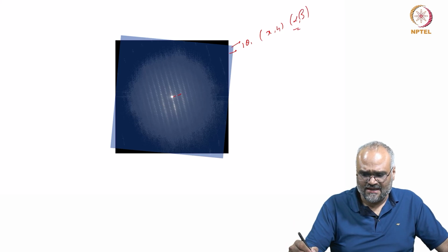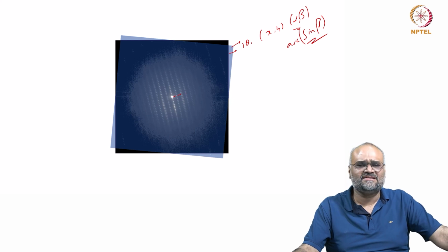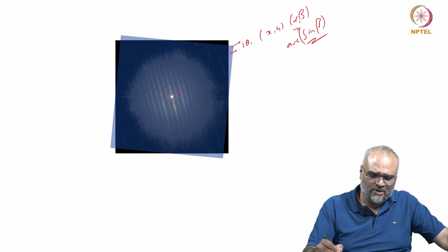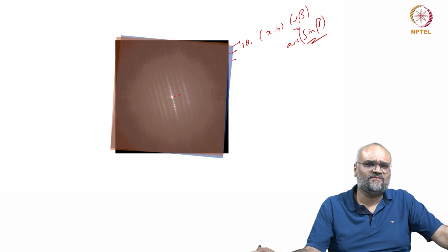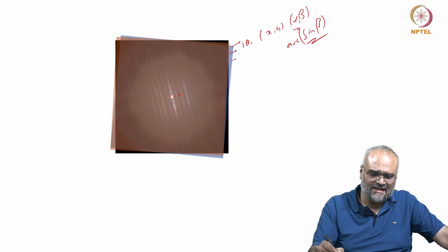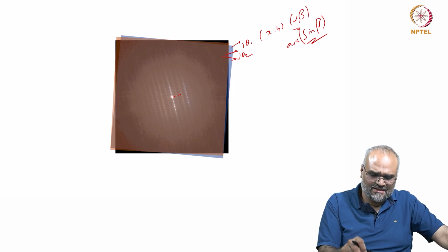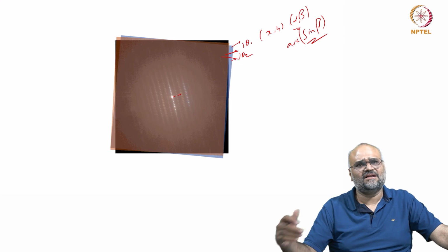Also using the inverse sine relationship that has been shared a couple of slides earlier, and then in between this reflection and the third set of reflections that I get from the diffraction pattern here, let us say my angle between these two is now theta 2. I can then measure these individual D1, D2 and D3 values and I can show them as projections on a graph paper.